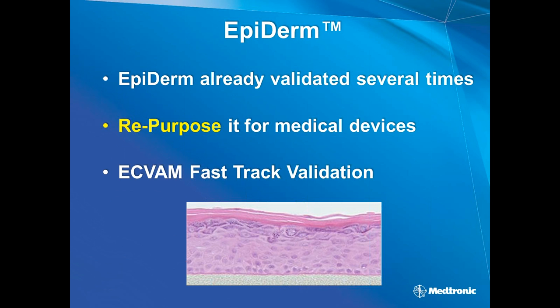So once again, we decided to stick with EpiDerm for what we're going to do, because it's been successfully validated several times for different sample sets of pure irritants. So it's very good at detecting irritants across the chemical space, which was important to us. And some people had approached us and said, well, why don't you include some of these other assays back here?